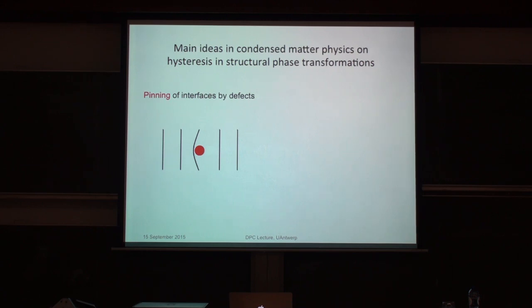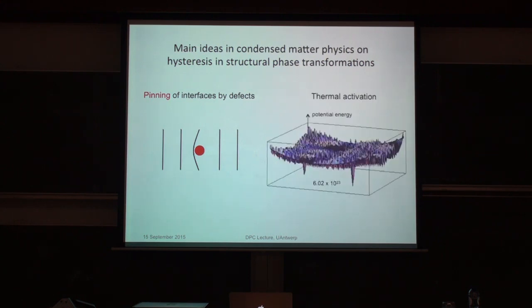One of the ideas is that when you have a phase transformation, you have an interface that separates the two phases, and it moves through the material, converting one phase to the other. There are inevitably non-transforming defects in the material, and this interface comes up against this defect. It requires an additional lowering of the free energy of the new phase to cause this to break through the defect. This happens both ways through the phase transformation, and therefore this is responsible for hysteresis. So many people would think this is an important aspect, and even in this ESOMAT conference, we have interesting talks about this aspect.